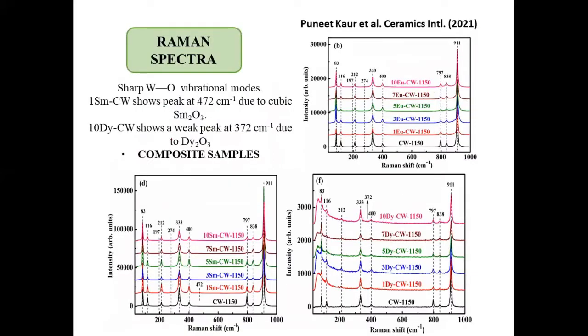Raman studies also confirm the existence of two distinct phases, of rare earth oxide and calcium tungstate. And all these Raman bands are due to the W-oxygen vibrational modes, either the stretching modes or the bending modes.